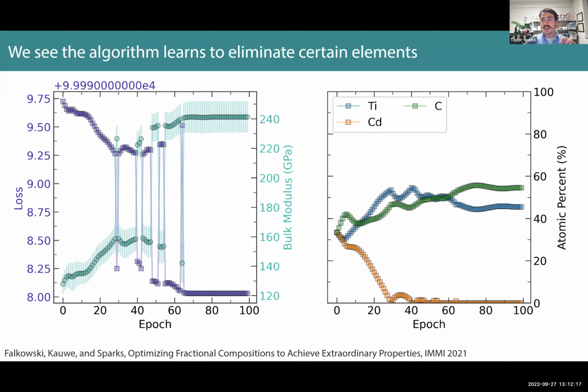But what's cool is that every step of the way, you can keep track of what that elemental prevalence was, right? What was the fraction of these different elements? You see that to start, we said that it was 1/3, 1/3, 1/3. We gave it titanium, cadmium, and carbon, all in equimolar amounts, so 1/3 each. And it learned to increase some and decrease others. In fact, to turn some off outright.